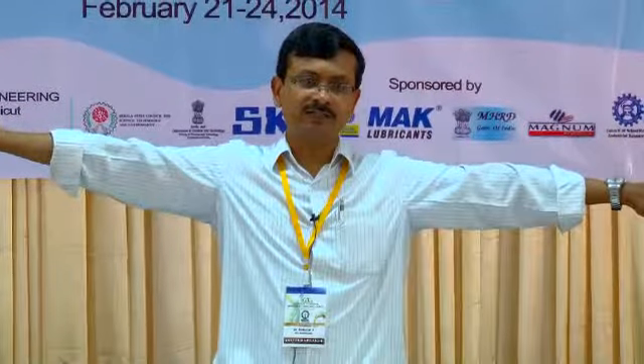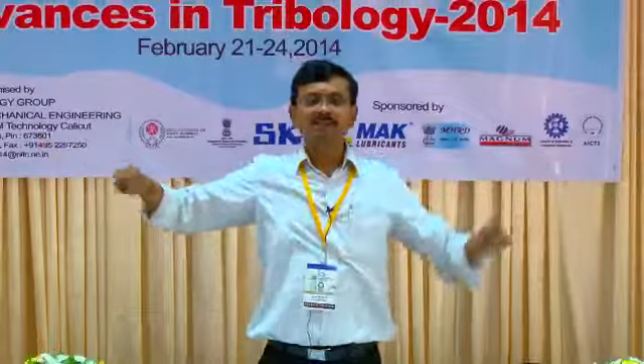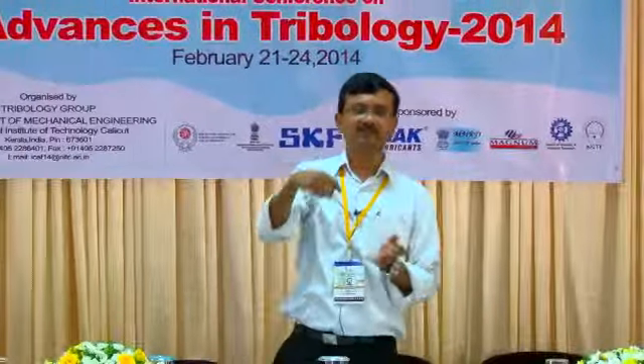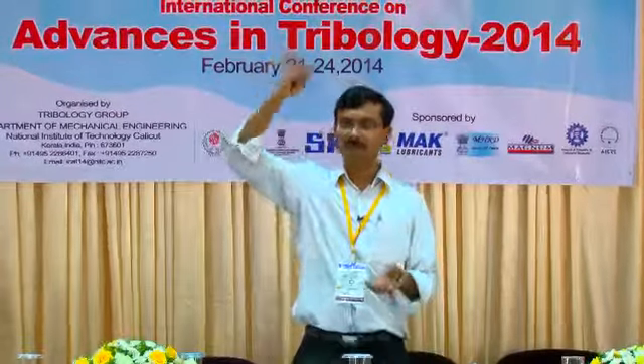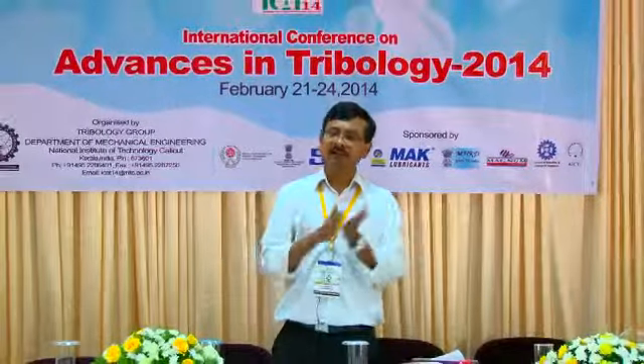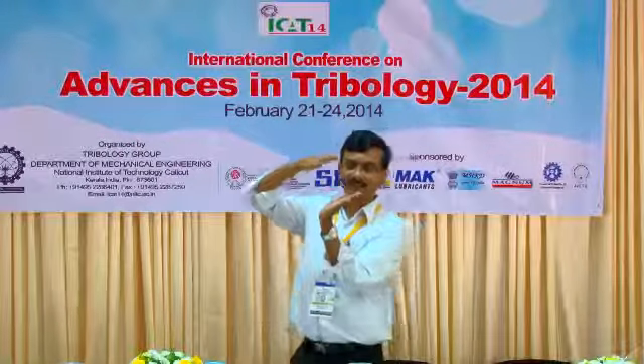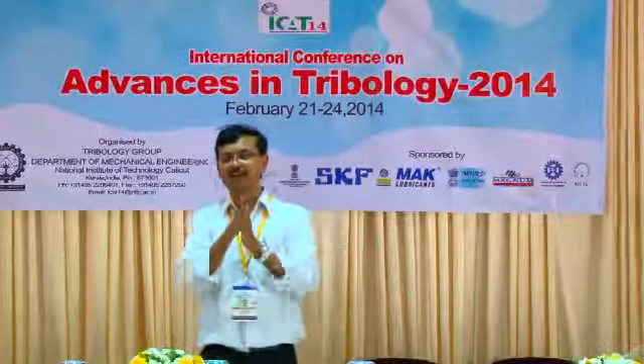This happened by accident. As the wear happens, the wear debris gets pushed away to the side at both ends. Suddenly some particles get dragged, possibly due to van der Waals forces, possibly due to the forces exerted by the electron beam themselves, by charging, local charging and things like that. So they get trapped, and trapping is not sufficient. They have to be repeatedly deformed within that gap to get a nice ball-like structure. But once the ball-like structure forms, there is an accompanying drop in friction.